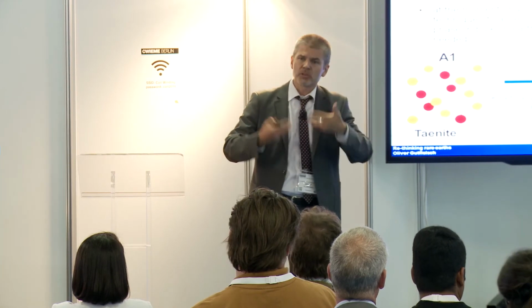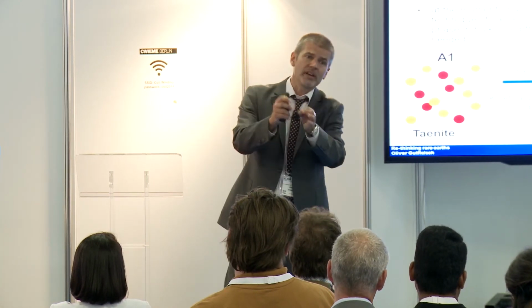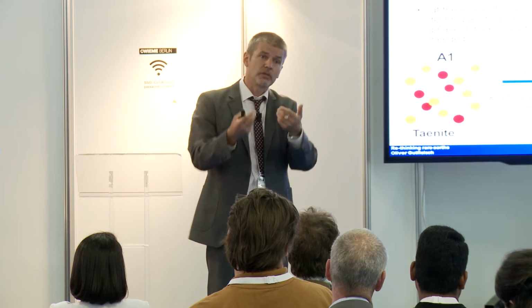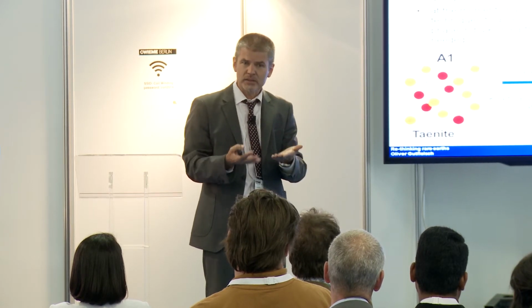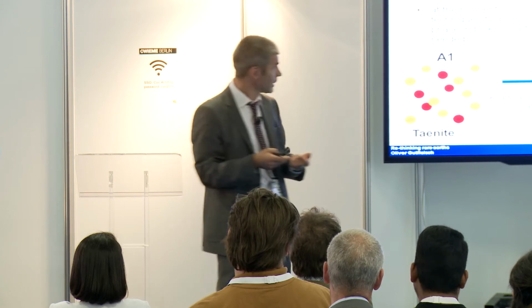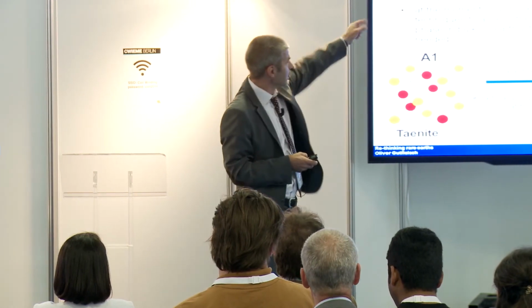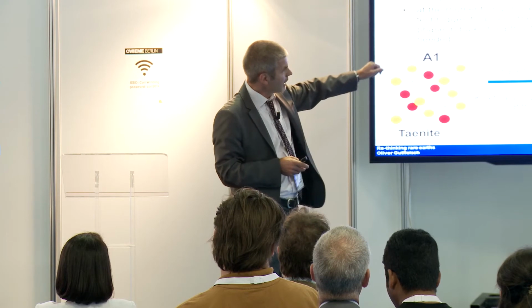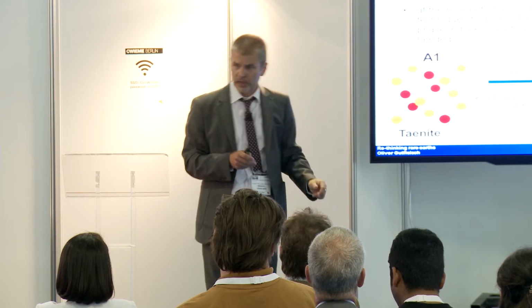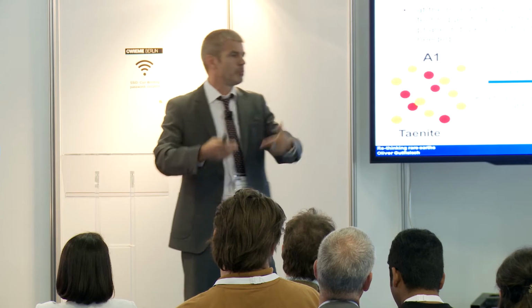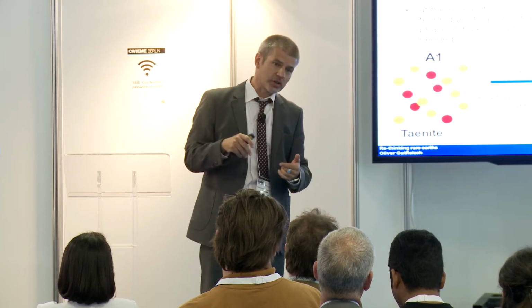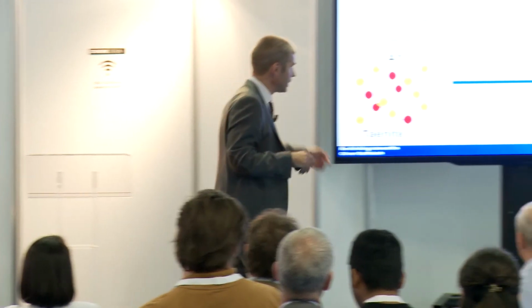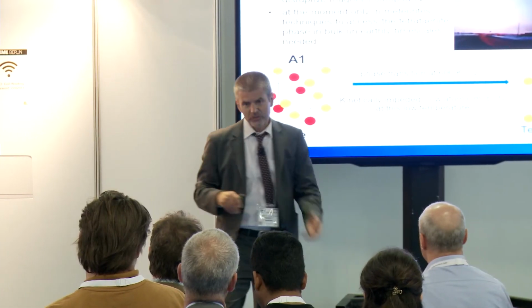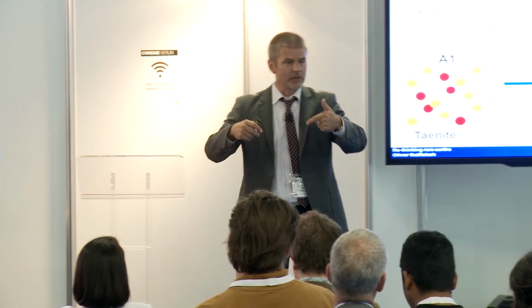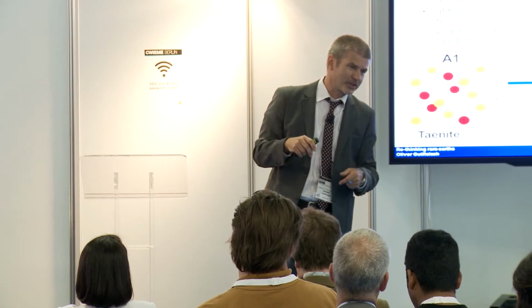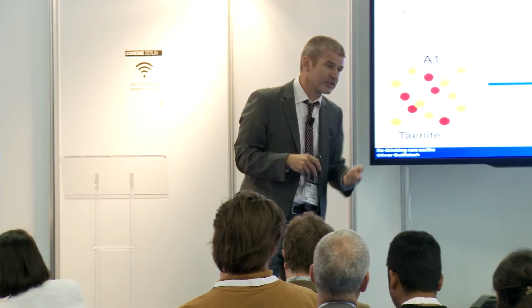L10 is a specific structure with a very high anisotropy. Iron platinum is used in magnetic recording. We need a very small amount of it, so we can afford it. But of course, to make a bulk magnet, it is not possible to pay for that. But for example, iron nickel is a cheap material. And you actually find it in meteorites. So they had billions of years to get into the right structure. The phase transformation we need is at very low temperature, so we have one jump of an atom going in the right direction every 10,000 years. So it's too long for a PhD or something.